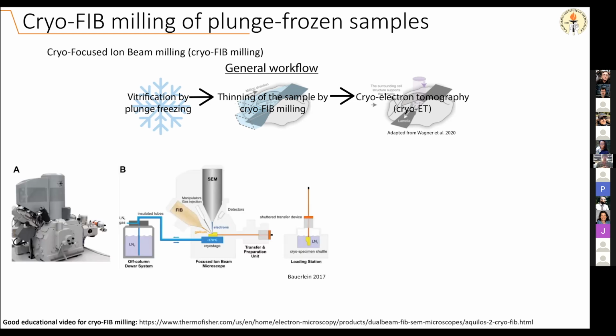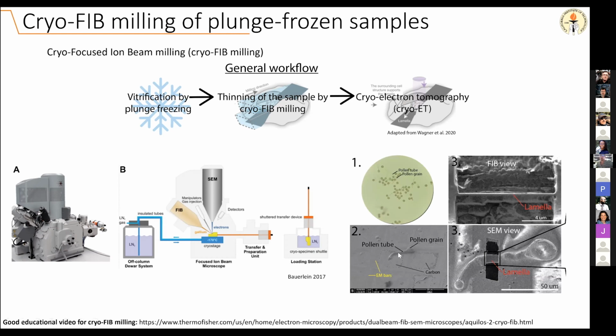So what exactly is FIB milling? Well, FIB milling takes place in a scanning electron microscope that is mounted with two beams, two guns, the SEM gun, that's the regular electron gun, and the FIB gun, which is a gallium ion beam gun. And so these focused gallium ions, they are very powerful, and they can erode the sample really fast. And so the game here is to take a sample that's too thick and to focus the gallium ions in rectangle shapes, and we erode away the sample, and all we leave is a really thin lamella that you can see here in panel 3. And this thin lamella is usually in the range of 200 nanometers in thickness, and that's amenable for cryo-ET observation.